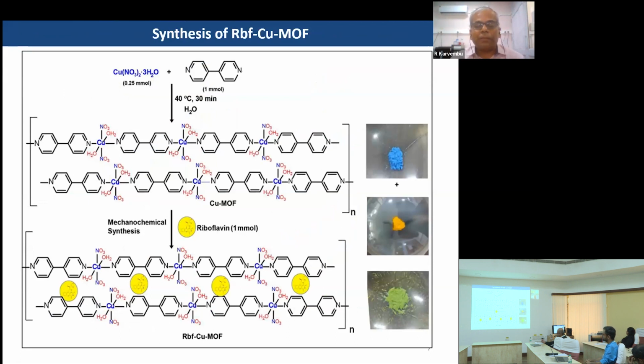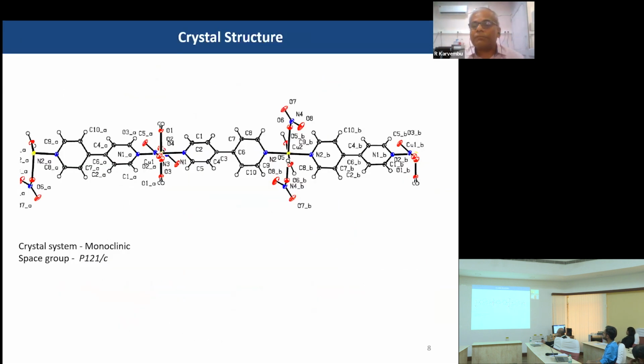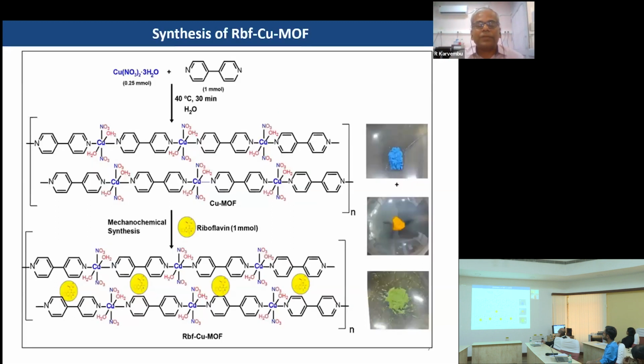This metal organic framework has been characterized by using various spectroscopic techniques. We could get single crystals of this copper-based metal organic framework, and we could solve its structure. Copper is octahedrally surrounded by 6 ligands: 2 nitrate ligands, 2 water, and 2 coordination sites occupied by nitrogen atoms of bipyridine ligands.